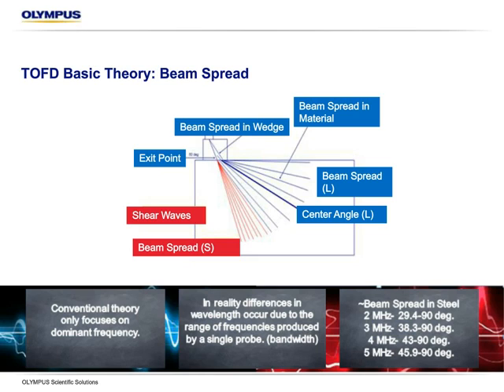For a variety of reasons we'll see, in the wedge we have a longitudinal wave. In the material we enter longitudinal waves with the center being at whatever angle the wedge is cut at. But in reality we have a whole big spread of longitudinal waves, as we can see in blue, and we also usually have shear waves occurring, which we can see in the red at about half that angle across the spread. So it's important that we are understanding of this.